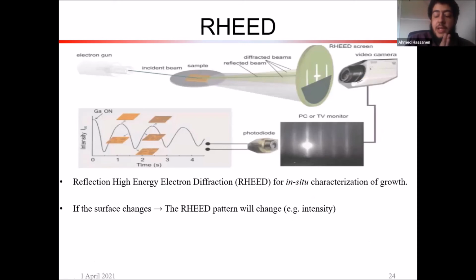And so to do this, we need a tool called RHEED. This stands for reflection high energy electron diffraction. It's very important for in situ characterization of the growth. It's a very important tool in MBE to characterize how the growth is progressing as it is progressing. Taking advantage of the vacuum conditions in MBE, we can have this electron gun, and we shoot this electron beam, and it grazes the surface that we're growing. Then it diffracts, causing a diffraction pattern. We can then capture this pattern with the camera, and this pattern can be a description of what's happening on the surface. So if the pattern changes, then something on the surface has changed.